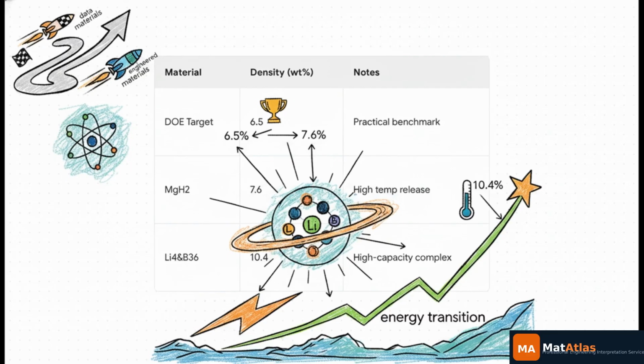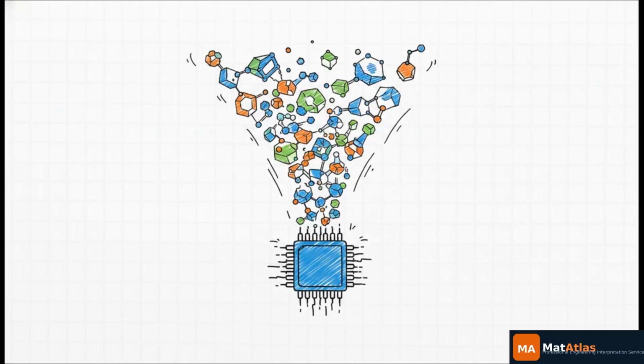The U.S. Department of Energy set a very strict practical benchmark for solid-state storage at 6.5% gravimetric density. As we just discussed, magnesium hydride clears that at 7.6%, but it fails on temperature. But look at the predicted capacity for our Saturn-like boron-lithium cluster, a staggering 10.4% by weight. I mean, if we can synthesize and scale complexes like this, it completely changes the math of the entire energy transition. And the discovery of materials like the lithium-boron complex, it isn't a fluke.